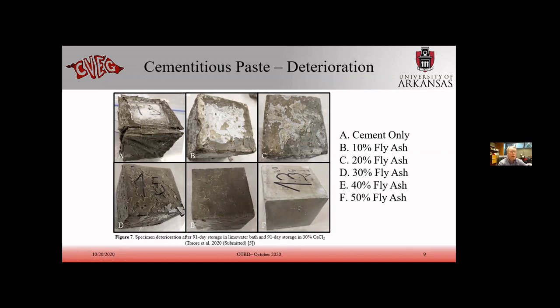So the idea is the fly ash comes in, it reacts with the calcium hydroxide, it consumes it and forms additional CSH. So if you don't have as much calcium hydroxide, you won't have as much of the calcium oxychloride that forms.